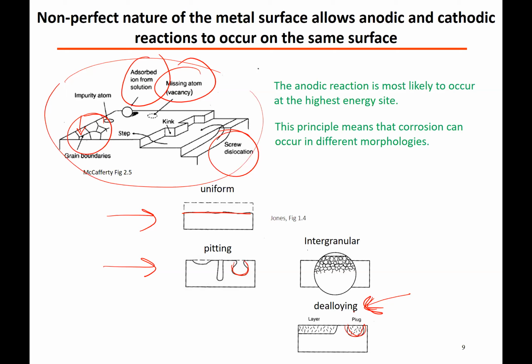And you can design it in a way that if you can preform the magnesium with certain configurations, with certain geometry, how it's distributed in your alloy, then once you dealloy it through a corrosive mechanism, what you get left over is copper with all these really interesting pitted structures like this. And that is actually quite useful for those working in the battery industry, because then you can basically put your active material, your cathode, your positive electrode material, into, let's say, these current collector electrodes, and then you can enhance efficiency and charge storage. And there's a lot of research and engineering that is involved in all of this. So corrosion is not always a bad thing. Corrosion by design is not necessarily a bad thing, to be qualitative and colloquial. It can be done in a way in which you can design it to your benefit.